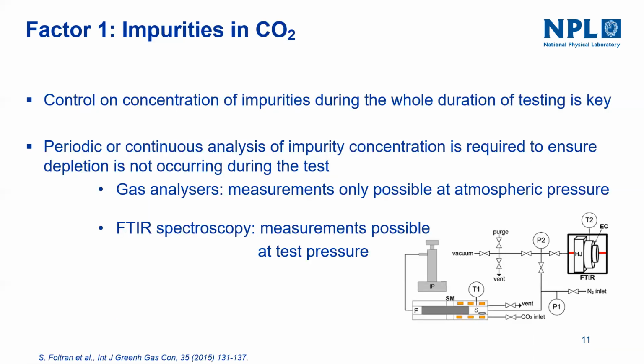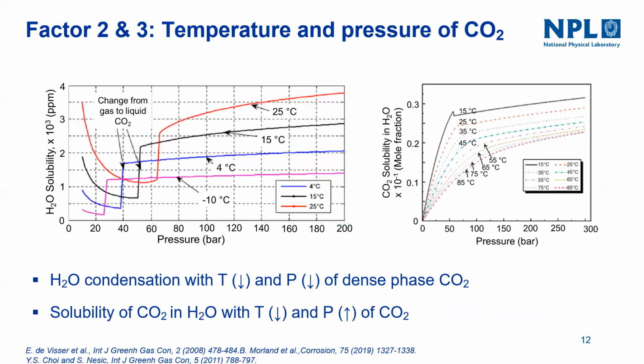And there's one more, like FTIR spectroscopy, which can be measurable at the test pressure, but there are more complications if there are more impurities. So right now it is completely not well established to measure the impurities during testing. And another factor is that during the testing, we need to have close control of temperature and pressure.